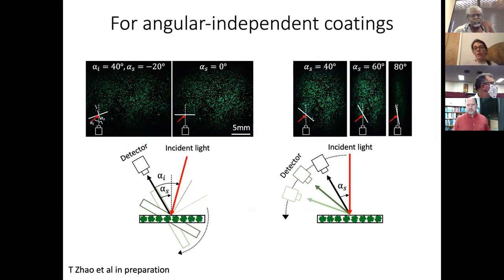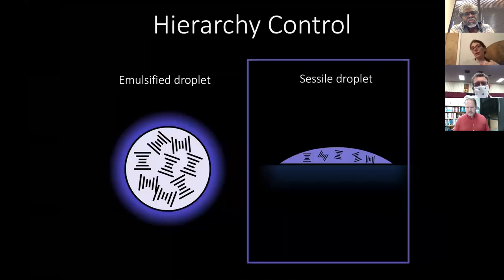And what is nice is that if you apply them as a coating on a surface, since you have this hierarchical structure, and you look at different angles, so these are all pictures taken in different configurations by illuminating the sample at one angle and collecting on another one, as you can see from the image, the color remains the same. And this tells you that even if the structure is periodic and you would expect a change of color, having this hierarchy allows you to get this nice angular independent response.